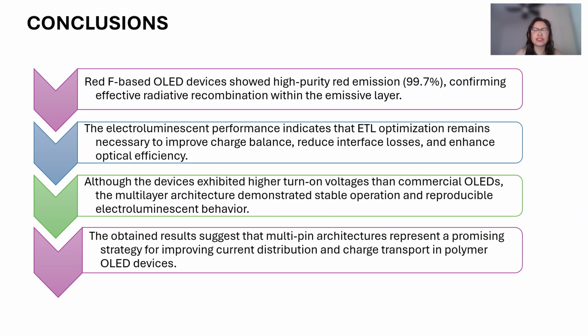Also, the device exhibits a higher turn-on voltage than commercial OLEDs. The multi-layer architecture has demonstrated stable operation and reproducible electroluminescent behavior. And finally, the obtained results suggest that multi-pin architecture represents a promising strategy for improving current distribution and charge transport in polymer OLED devices.